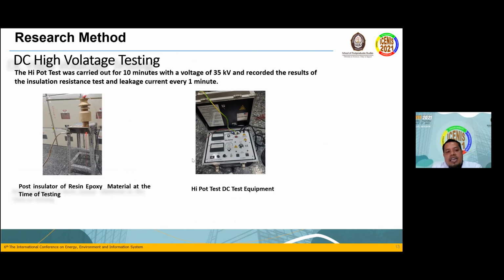And then the high voltage DC testing, for 10 minutes with a voltage of 35 kV, recording the result of the insulation resistance test and leak current every 1 minute. This is the post insulator designed to separate, and this is the test equipment.